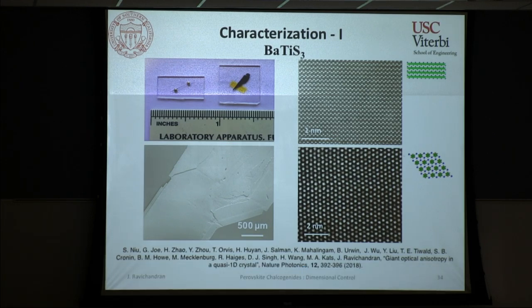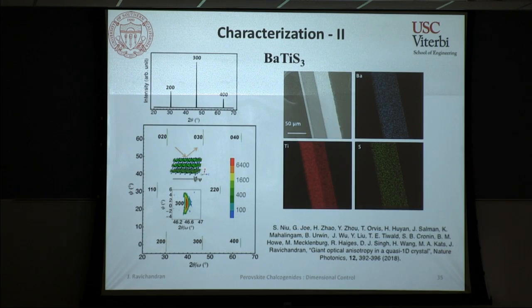So then we got curious, and we wanted to know what is the crystallographic direction for the crystal plate that we have seen. Okay, so my student spent some time and started trying to figure out how this works. When we did the out-of-plane diffraction on these crystal plates, we found that it has A-axis orientation.